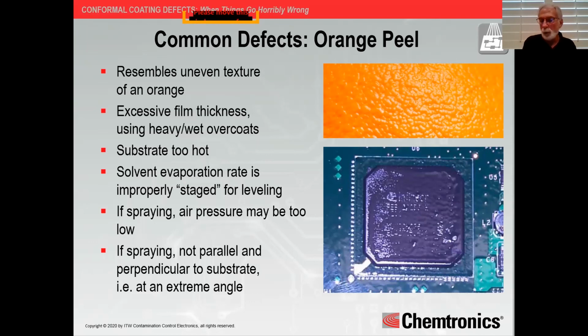Sometimes if you have a wet coat and you're applying another coating on top of it, that pressure from an aerosol, from a spray gun can kind of push it. And as that bottom picture, you can see the coating on the left-hand side looks thinner and it looks like it's been waved up over to the far right-hand side. And you can see kind of the peaks and the valleys and that uneven texture there.